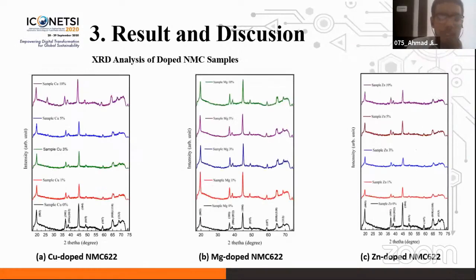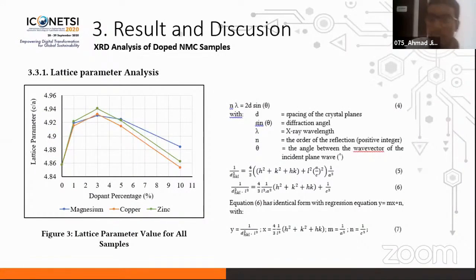Next, for the XRD analysis of doped NMC samples, as shown in the figure, it can be observed that almost all of the samples have peaks identical to pure NMC. The sharp peaks at 2 theta angles of 15 and 20 degrees and 40 degrees indicate that the NMC material has high crystallinity, except for NMC with copper content of 5% and 10%. There is a new peak at a 2 theta angle of around 25 degrees, which indicates the presence of a copper oxide phase. Based on the figure, we can conclude that the doping of magnesium and zinc was successfully conducted with no secondary phase detected, while the copper doping is successful when the concentration of copper is less than 5%.